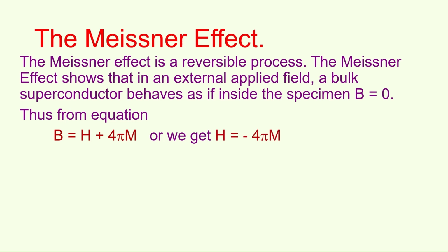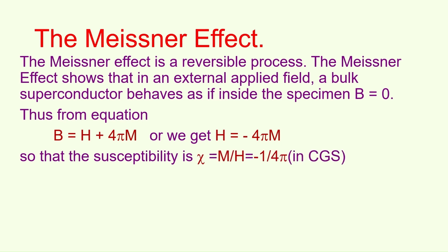The Meissner effect shows that in an external applied field, a bulk superconductor behaves as if inside the specimen B equals 0. Thus from the equation B equals H plus 4 pi M, we get H equals minus 4 pi M, so that the susceptibility is chi equals M divided by H equals minus 1 over 4 pi in the CGS system. And in the MKS system, chi equals M divided by H equals minus 1. A negative susceptibility, that is, a superconductor exhibits perfect diamagnetism.